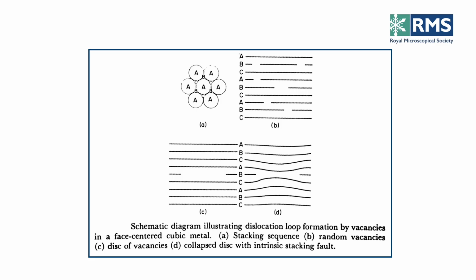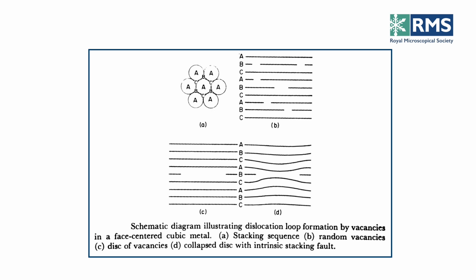If you consider a metal near the melting point, there is a much higher concentration of vacancies in thermodynamic equilibrium than there would be at room temperature. That's a question of entropy, really, disorder. This picture shows you what would happen if you take such a material from near the melting point and quench it down to, say, room temperature. In order to get rid of these excess vacancies, they congregate into disks, which you can see in little c here, and this disk will then collapse to form a dislocation